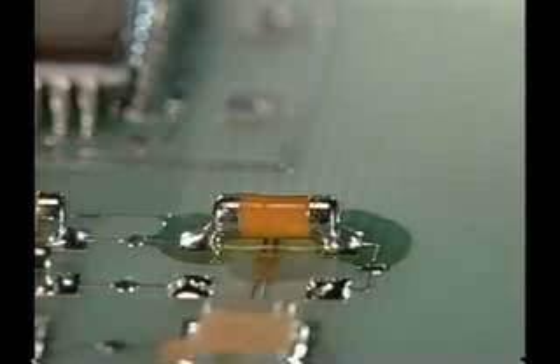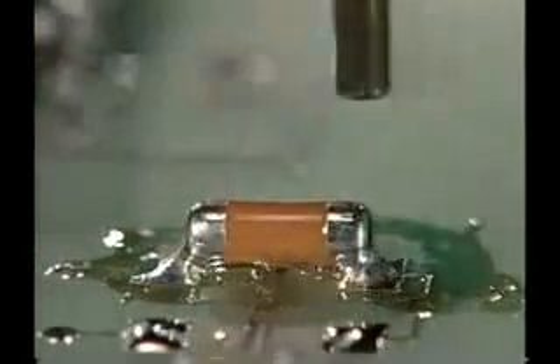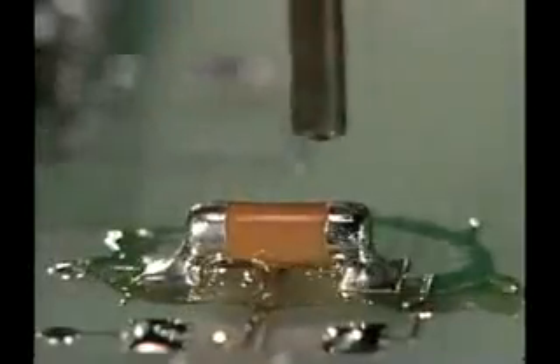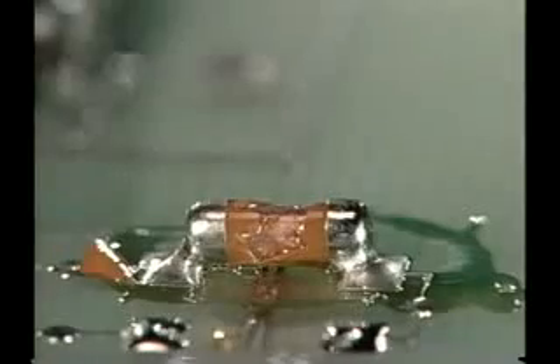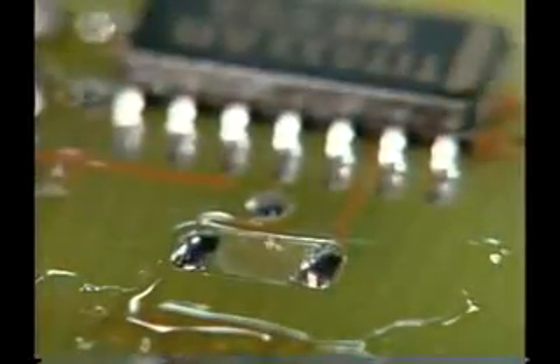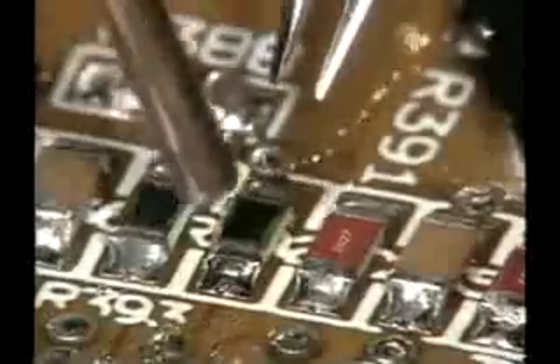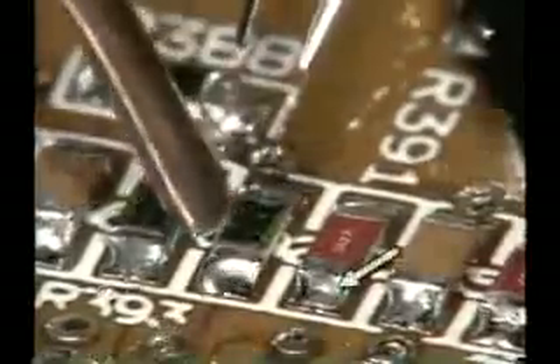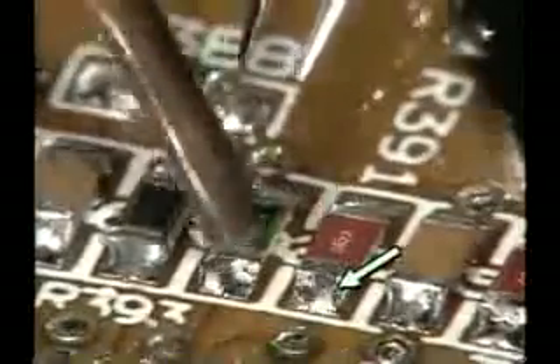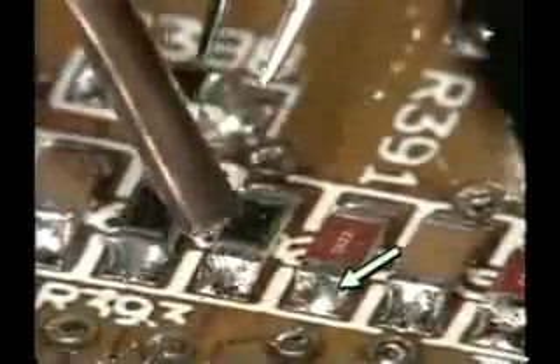The first being that you have to be sure that both joints are completely melted before you attempt to remove the component with the tweezers. If you try to remove the component too soon, the lands or the component can be damaged. If the air pressure is too high, the component and the solder can be blown right off the lands. This can create additional rework. Too much pressure can also reflow adjacent solder joints. Even if they don't get quite hot enough to melt, the solder can become brittle from excessive reheating.